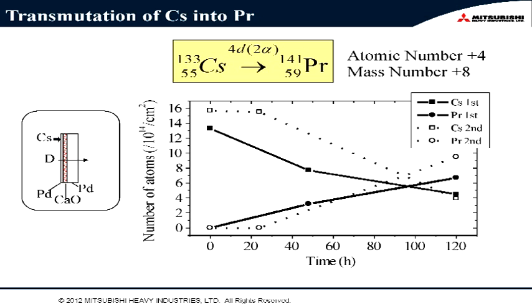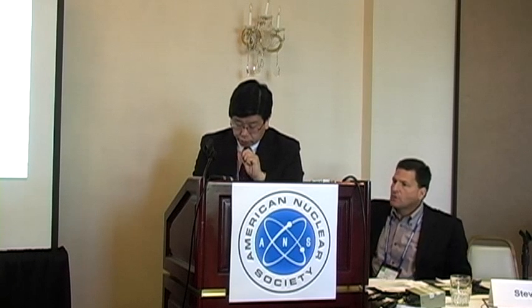So we understand that in this experiment, cesium transmutes into praseodymium. And as I said, in this case, the atomic number increased by 4 and the mass number increased by 8. But if we omit cesium, or deuterium, or calcium oxide, we do not observe this transmutation.